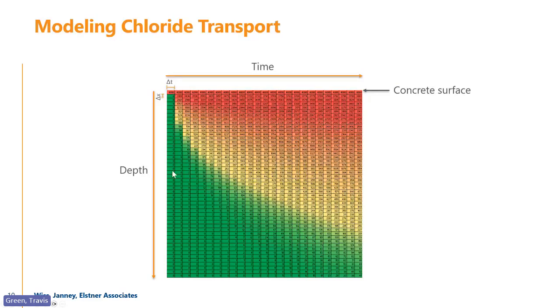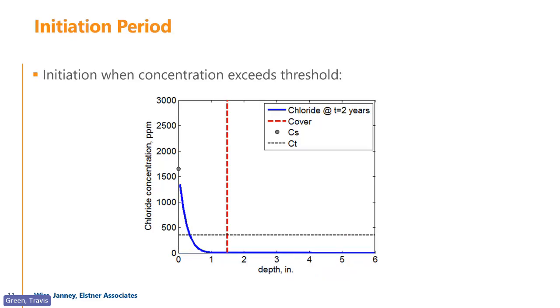But nothing else through the depth has chlorides in it, right? But over time, those chlorides diffuse by Fick's law. And as you get farther and farther along, right? This horizontal is the concrete surface, time is to the right, depth is down. So those chlorides diffuse down, right? And we get more and more chlorides down through. And at some point down here, right, our bars are going to sit there, yeah? So at some point, we're going to start to see chlorides at the bar level, and that's potentially going to result in corrosion if we exceed these kind of threshold levels.